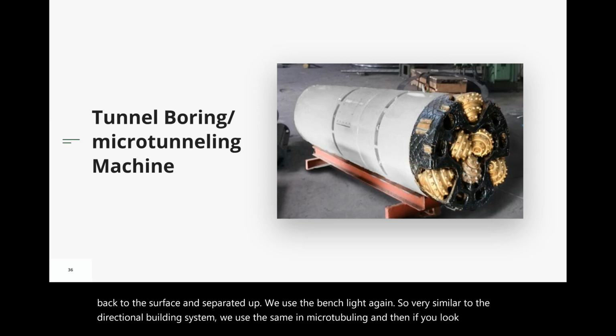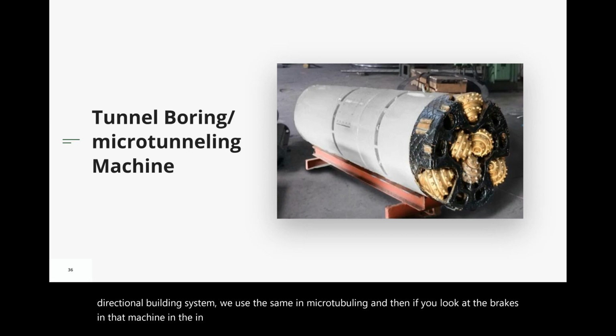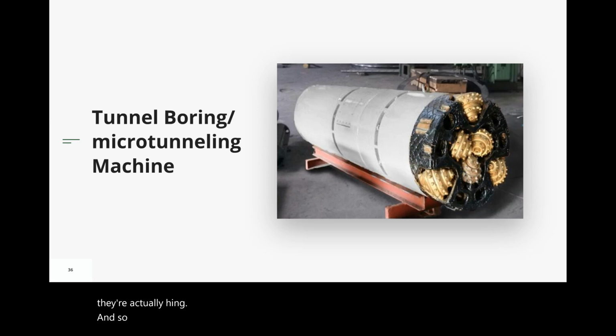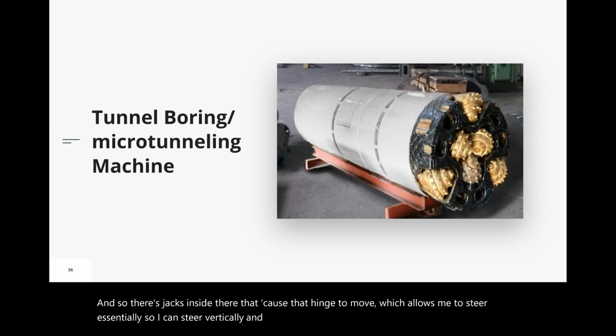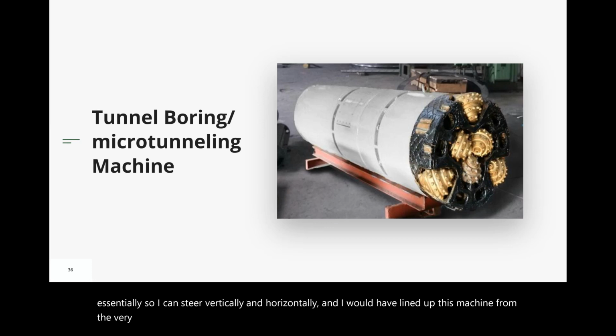And I'm shipping in bentonite from the very back into the front, out into that cutting edge there, mixing with the cuttings that are coming off the rock as a result of those wheels that are chipping away at the rock all the time. And those cuttings are tending to flow to the bottom. They go in, you can see the holes on the bottom there. Those cuttings get absorbed in through there, or they flow in through there because it's pressurized, and those cuttings then are pulled back and back up to the starting process and put through cleaners and take the cuttings out.